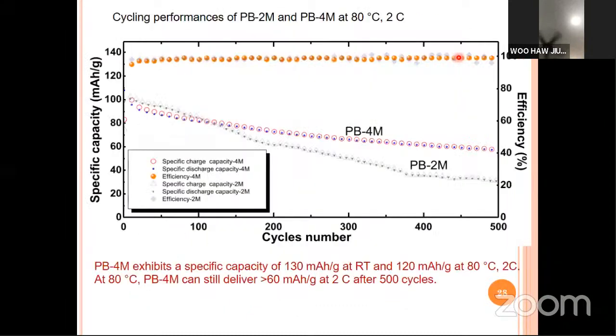What about for long cycles? Well, this is the result for PB-4M. We run it at 2C rating at 80 degrees. This line shows still more than 60 milliampere hour per gram after 500 cycles.